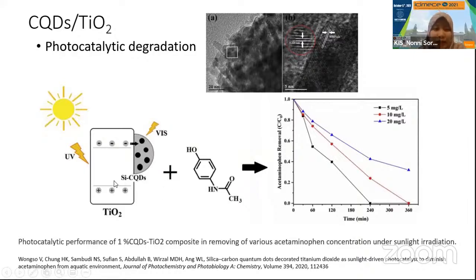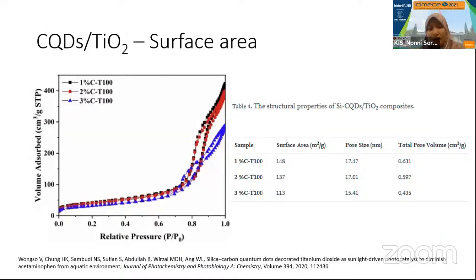Okay. And in the combination of the carbon quantum dots that we have synthesized from the rice husk, we combine it with titania, and this time we try to degrade acetaminophen. Right? And this time we try to be more ambitious. So we did the experiment under the sunlight irradiation. Okay, so before we go to the performance, what are the characteristics of the combination of these carbon quantum dots and titania that we found?